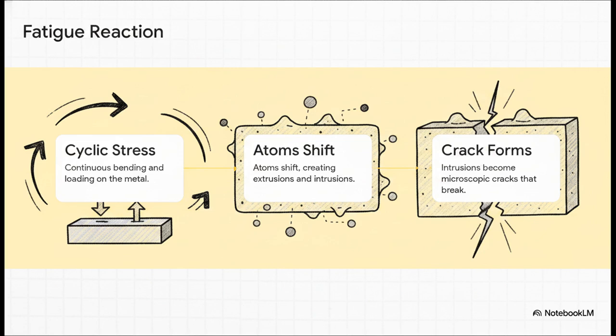Step 2 is where the real damage begins. Because of the stress, localized groups of atoms either push outward, creating what we call extrusions, or they cave inward, creating intrusions. Basically, imagine the surface getting these tiny microscopic wrinkles. An intrusion is essentially a microscopic surface wound, and eventually, step 3 kicks in. That tiny little intrusion becomes the birthplace of a microscopic crack. As the machine just keeps running, that crack zips through the metal until snap.